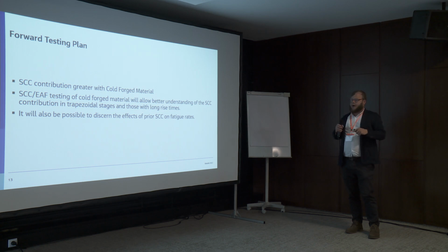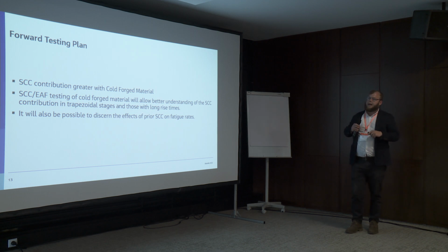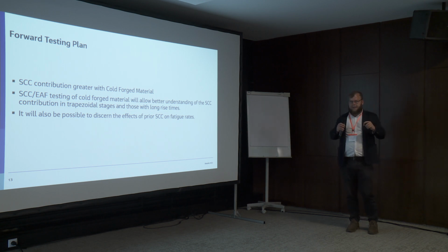So that was a summary of where we're up to with the testing. It's an incomplete testing program at this point. We've completed some tests, but we've not yet post-test corrected the data. We've tested 15% cold forged material under the combined SCC and fatigue loading, so we can turn up the SCC. We've done it at a higher temperature as well, so we've turned up the SCC in this test to really be able to pick out the contribution of SCC in these trapezoidal loading stages. And we've also gone back into fatigue stages after that.